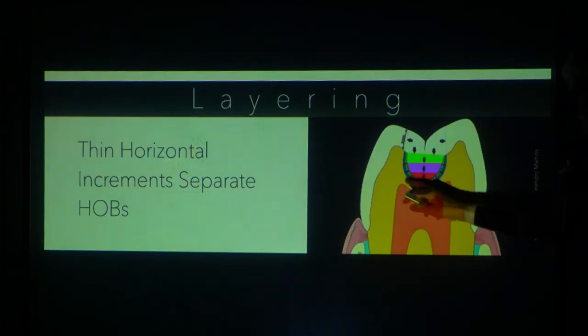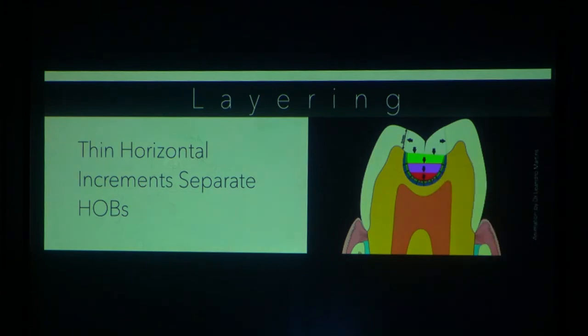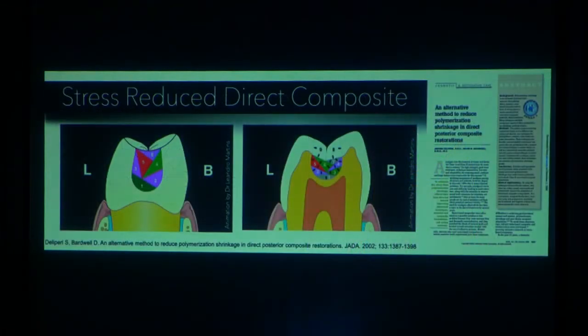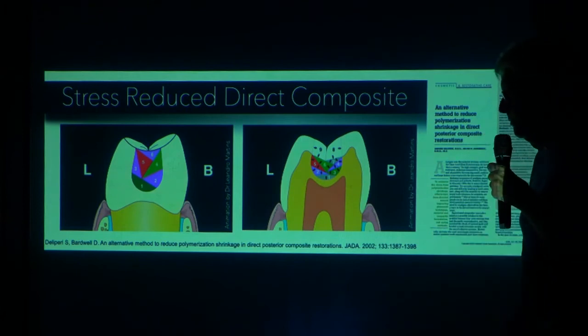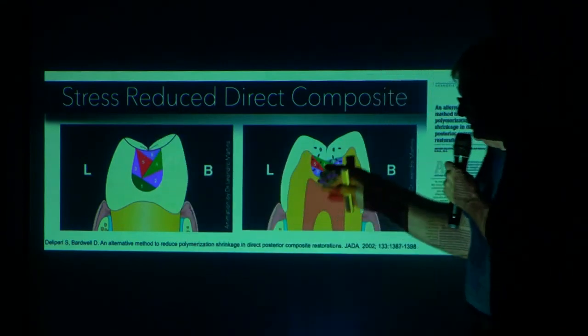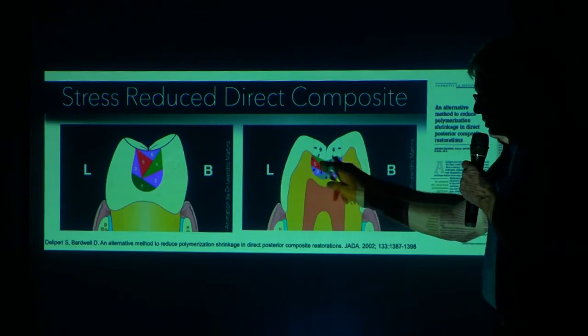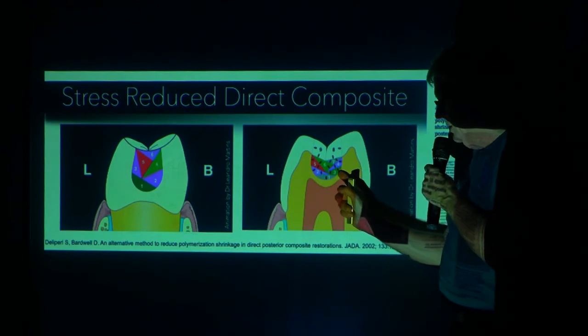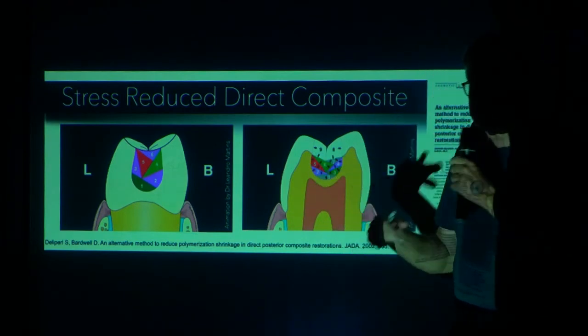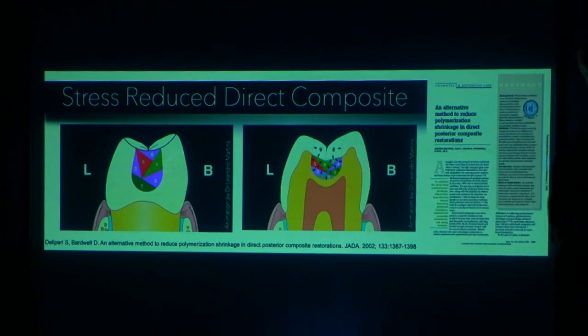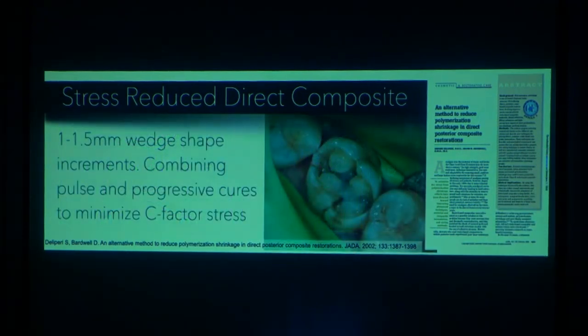And so this little illustration adds this second concept of placing fiber. And if we place fiber in these thin horizontal increments, this is the technique that Simone Della Bona and I have developed that we call the wallpapering technique. But Simone, when he published his paper with Dave Bardwell in 2002, showed a technique of creating a wall, interproximal shell first, and then doing a dentin replacement with, in this situation, seven increments of composite. Instead of 4 increments, 7 increments does even more because we're only putting that increment of composite towards one wall, basically. And that's a classic paper that needs to be read by every biomimetic dentist. 2002 Journal of the American Dental Association.